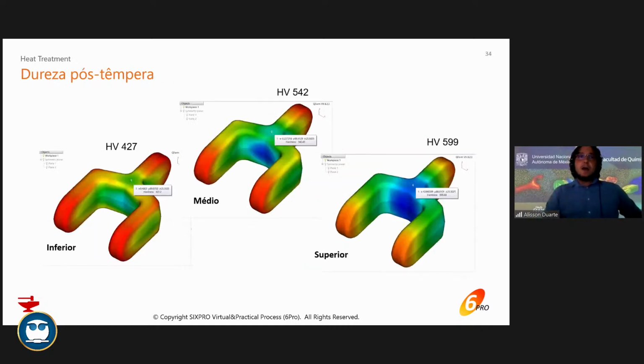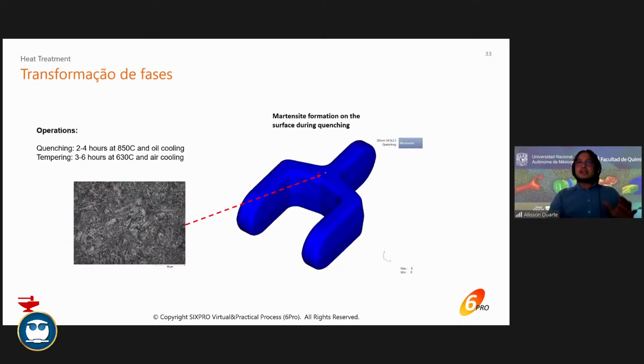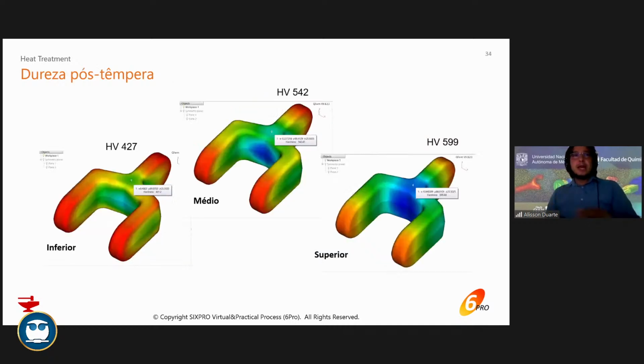Well, we did also one trial because, let's say, you have a specification of hardness, and you say, okay, I have my process here, very good. However, the material has this range of chemical composition, and that changes everything. That changes the transformation curves. For example, for the same alloy, if I get the bottom limit of that alloy and the upper limit of the same alloy, you see that at that point, I can get from 430 Vickers up to 600 Vickers, which is very wide, sometimes not acceptable,